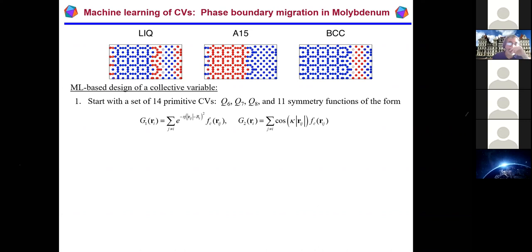So what we did was introduce a set of classifying functions that we can use to classify local environments. After all, we have an interface, so we need local information around this interface. And a good way to do this in a way that's translationally and rotationally invariant is to use symmetry functions along with the standard Steinhardt packing order parameters, right? And these come in as surrogates for your atomic coordinates. These are also the kinds of things used in generating neural network potentials.